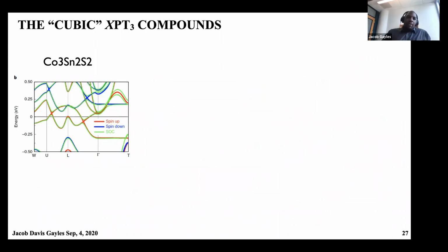So back to the band structures, we come back to this cobalt 3 tin 2 sulfur 2, and here is a quite simple band structure. You can see here we show the majority versus the minority with spin orbit coupling. And here, once adding spin orbit, you can see the gaps open, but it's not a drastic change in the band structure from the magnetic case with no spin orbit coupling to the case with spin orbit coupling.